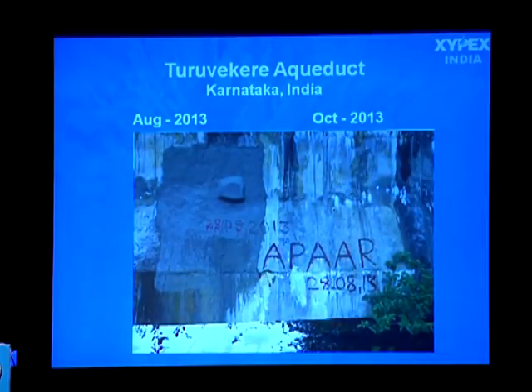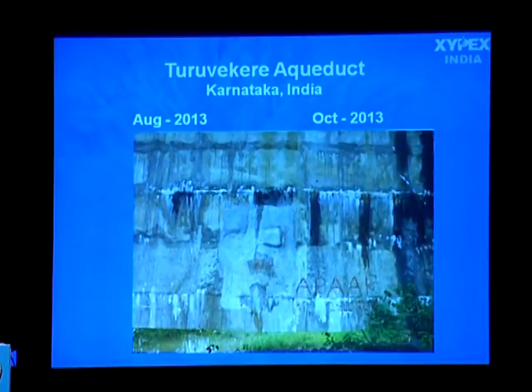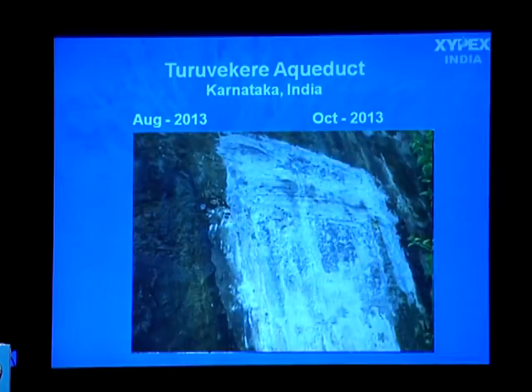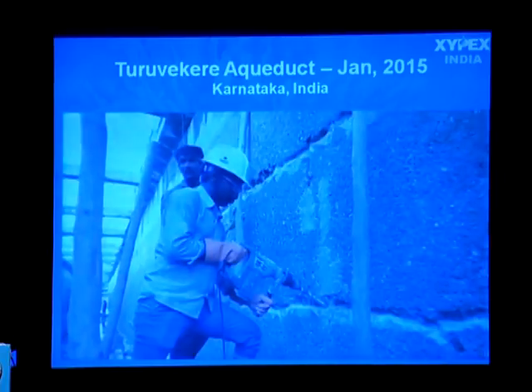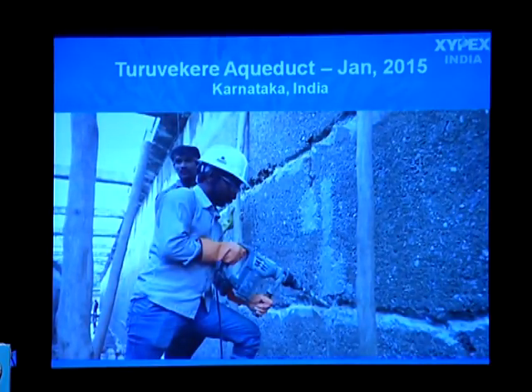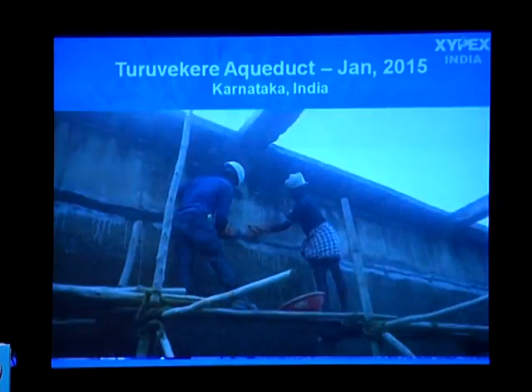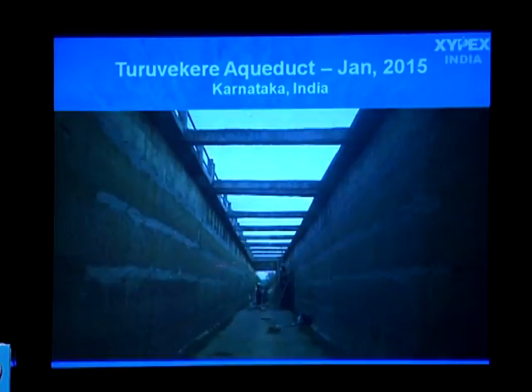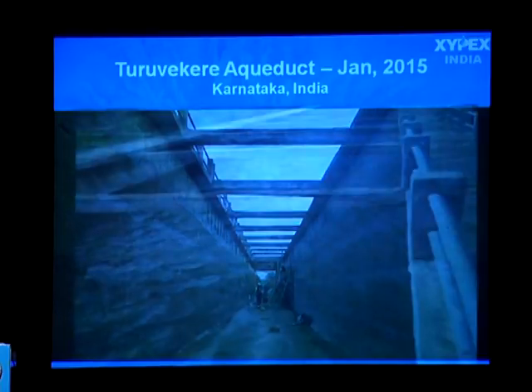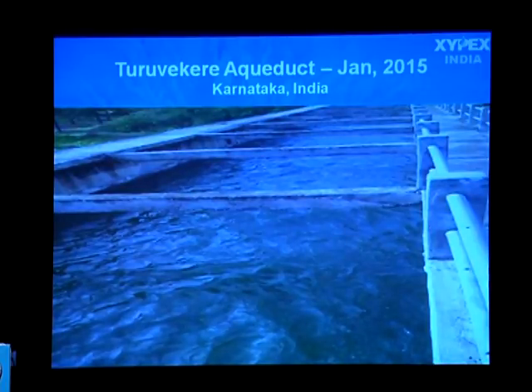In October 2013, when we went back, we found that the entire area where the water was actually leaking was rendered dry, and then we can see the patch. It was completely dried out there. As a result of that, we got awarded this first job in Karnataka in Turuvekere Aqueduct, where we treated all the joints using our high-strength repair material. We grouted all the weak areas along the joints on both sides of the structure, and thereby, as of now, as I speak, we have been able to maintain the required level of the irrigation water.